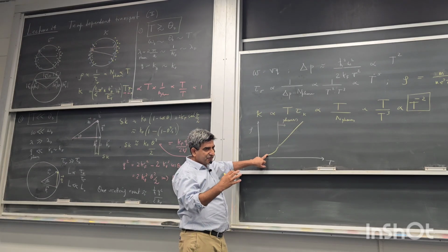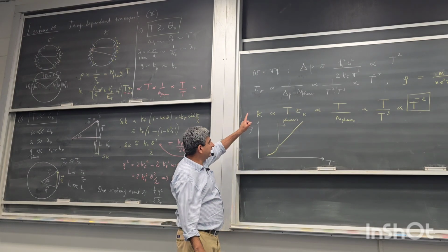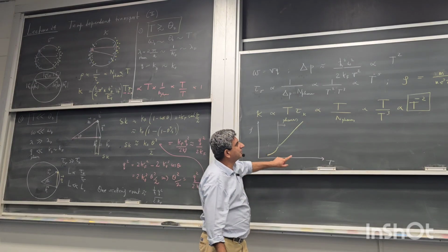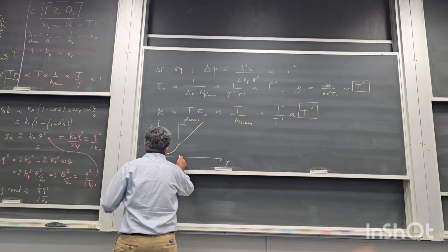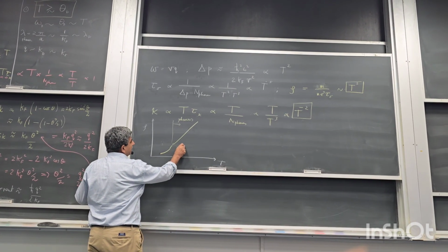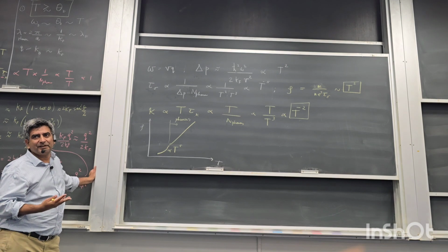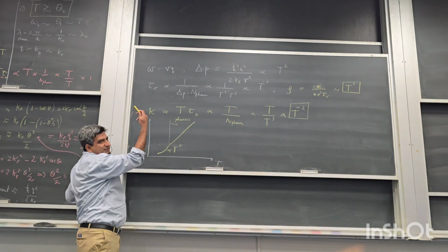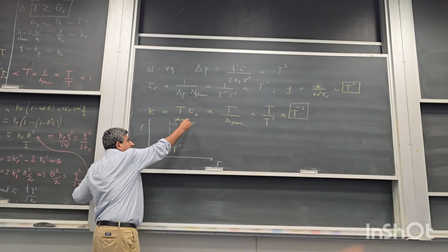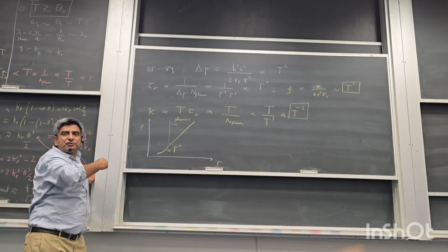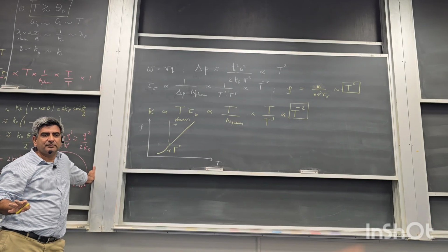So we have inefficient processes. Therefore, we've already indicated that in this regime, the resistivity now varies as the fifth power of T, or ideally it should, at least theoretically. So this is a curve for the ideal resistivity. Our scattering mechanism gives us a relationship of this kind, solely describable by electron-phonon interactions.